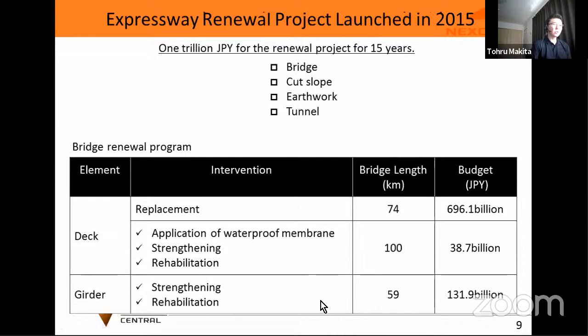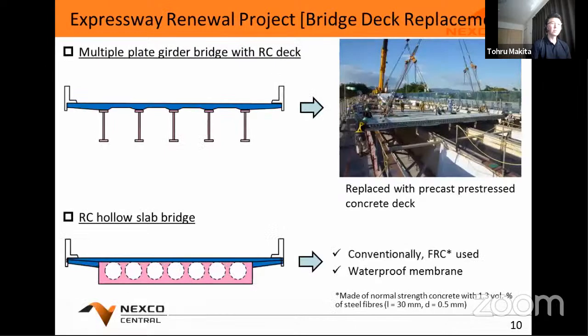So this table shows the bridge renewal program in the renewal project. Bridge deck replacement is undertaken the most extensively. In the case of steel plate girder bridges, RC decks are removed and replaced with precast prestressed concrete decks. In the case of reinforced concrete hollow slab bridges, deteriorated top surface concrete is removed and the top surface of the slab is rebuilt. As the rebuilding material, fiber reinforced concrete is conventionally used.